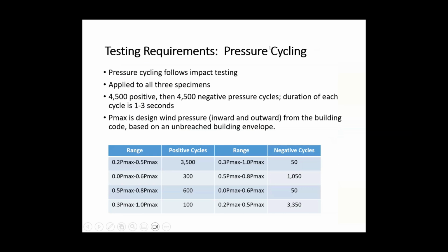So the pressuring is pretty simple. You test it 4,500 times in the positive direction and then 4,500 times in the negative. Each duration is 1 to 3 seconds. And normally you have to work with an engineering firm to determine what pressures to use for each of these different cycles. But basically, you have to cycle the glass 9,000 times and have none of the glass pull out of the frame.